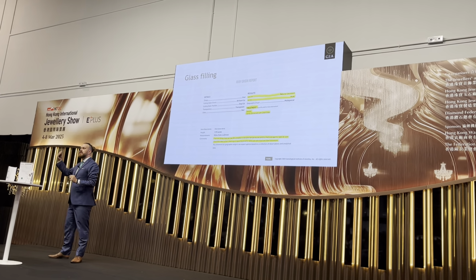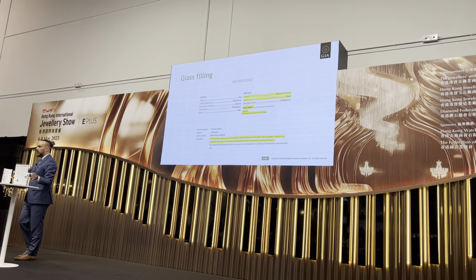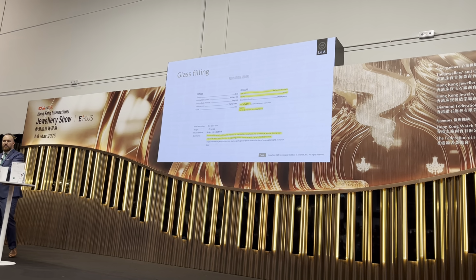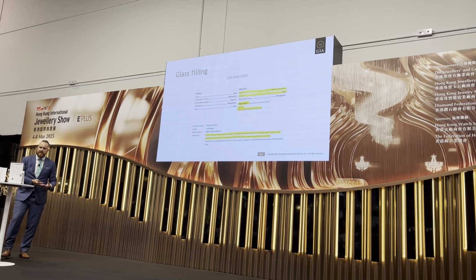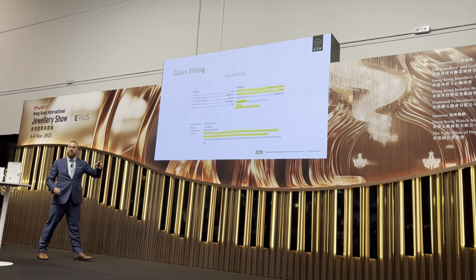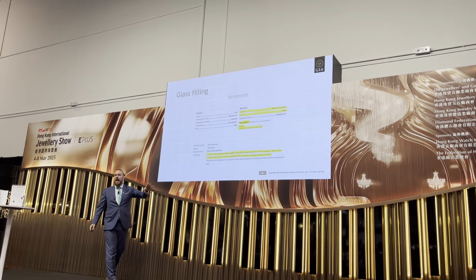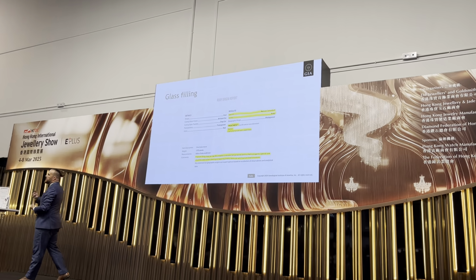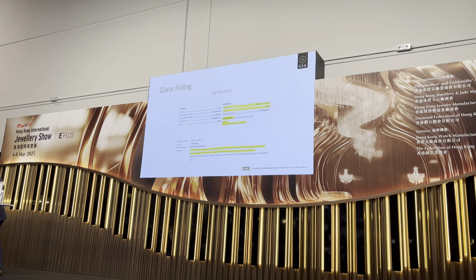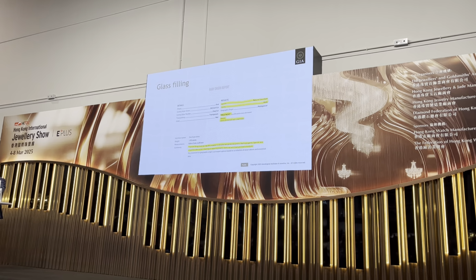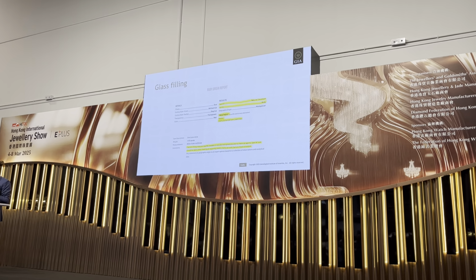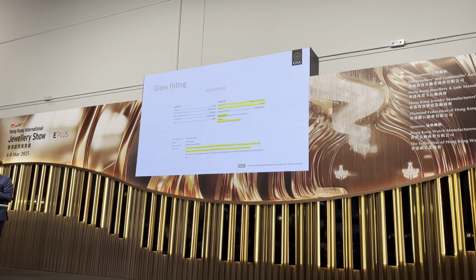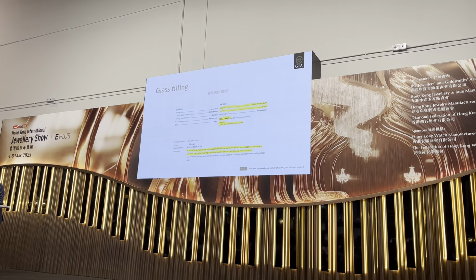So this is actually the same process that we do in emerald, just with a material that is suitable for corundum, in this case lead glass. But it does come with this statement that this fracture filling material may be unstable at higher temperatures and to chemical agents, and special care should be taken when cleaning or repairing jewelry with these stones.